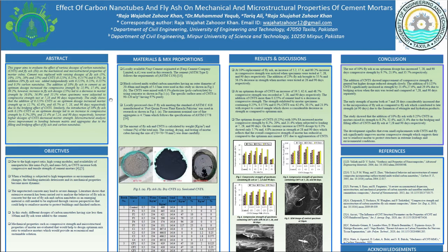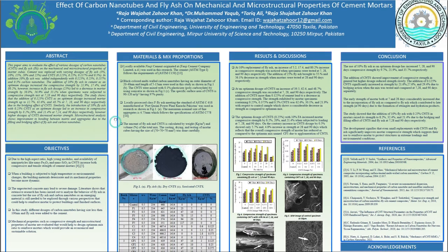The study also shows that reinforcing mortar with carbon nanotubes — even small replacements — can enhance the compressive strength of cement mortars up to 12, 62, and 48 percent at 7, 28, and 90 days respectively. Microstructural analysis further showed that mortars containing carbon nanotubes had better bonding with aggregates and a better bridging effect.